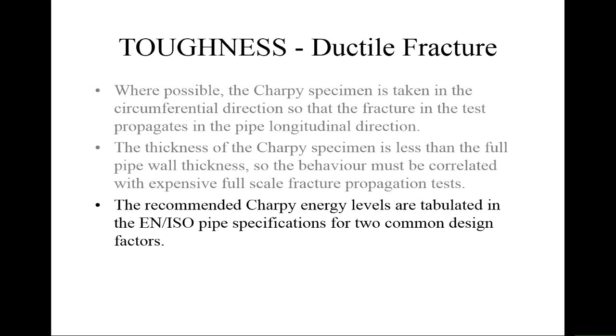So you have to be careful when you look at specifications that they are performance specifications, and therefore if you pick up steel from one manufacturer and steel from another manufacturer, they aren't necessarily the same. And steel from one manufacturer one year might not be the same as steel from the same manufacturer to the same specification another year. And that's not such a problem when you're dealing with these easily quantifiable tests like strength tests and toughness tests. But if you're going to weld those materials, sometimes the welding procedures will change because the steels are no longer identical, and you have to do some qualification tests.